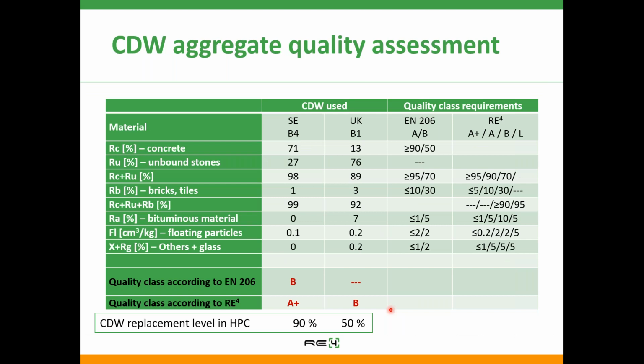And the reason for this is that these two different CDWs have different quality. This will be an issue for a later webinar, but shortly, the quality class of CDW as used in concrete is stipulated in the EN standard for concrete, EN 206, with two different classes, A and B, where A is the better one. The more concrete and unbound stone you have, the higher the quality, and more bricks and tiles and bituminous material generally lowers quality. Looking at these two batches, SE and UK, with the present system, EN 206, the SE batch is a B class, and the UK doesn't even qualify, and this is reflected in the amount we can replace.